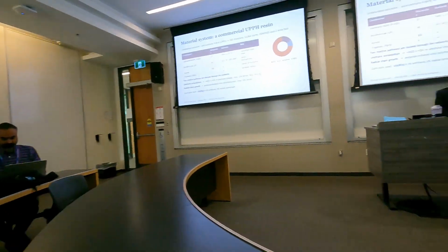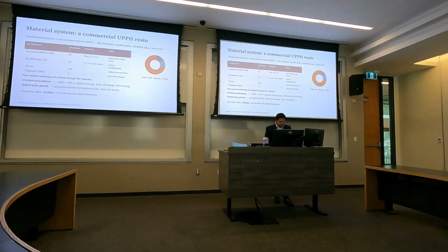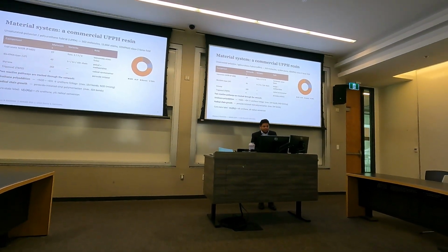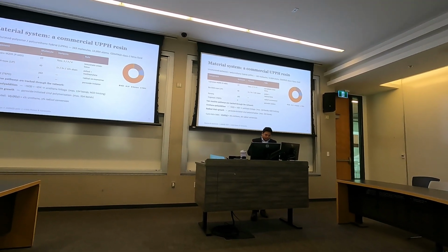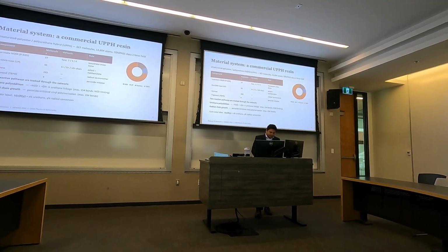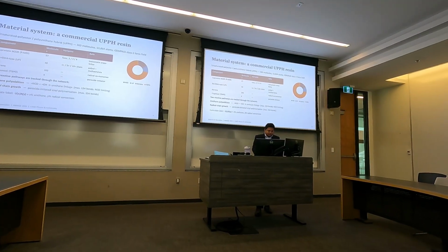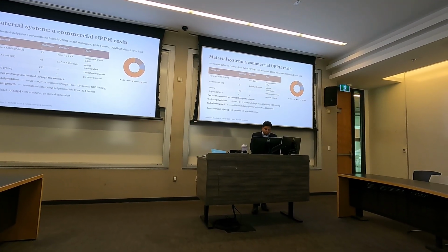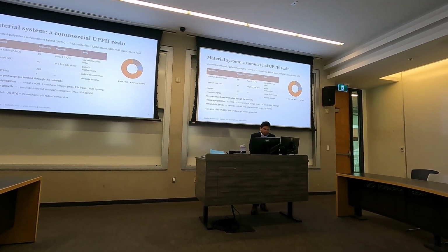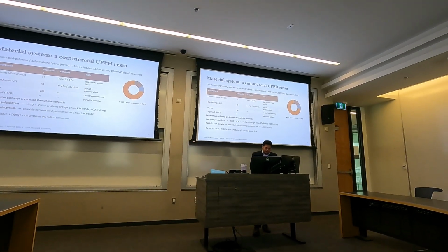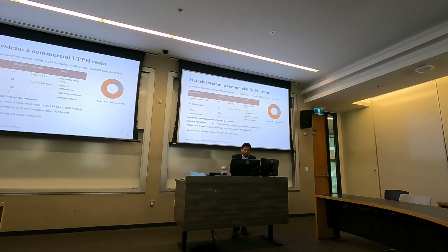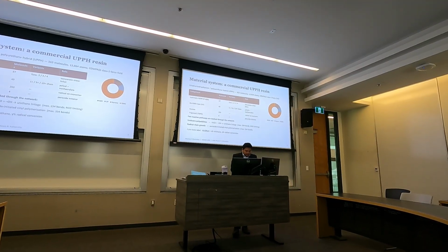In the simulation that we are running, we have around 14,000 atoms in our simulation box, and there are 4 key ingredients: one is the isocyanate cross-linker with different functionality, a polyol that also carries methacrylate vinyl groups, styrene, which is a co-monomer, and a peroxide initiator.